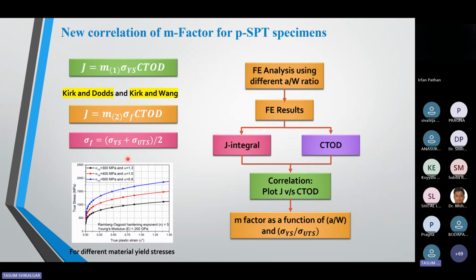How much path you are using to calculate this ahead of the crack tip is also important. So these type of correlations between J integral as well as CTOD are available only for CT and 3-point bending specimens, which are published in the ASTM E1820 standard. But these correlations are not available for miniature specimens. So I decided to generate this type of correlation, known as the M factor. I decided to find out the M factor for my specimen, the PSPT specimens.